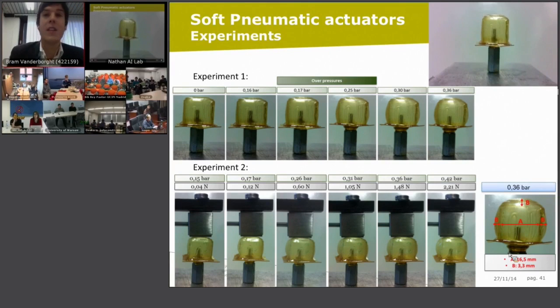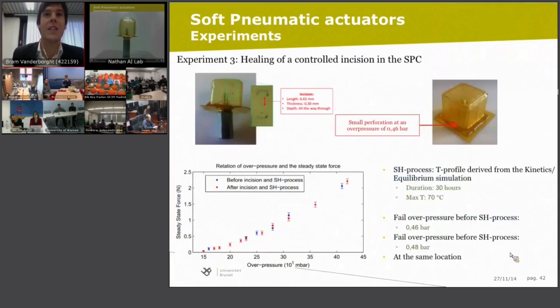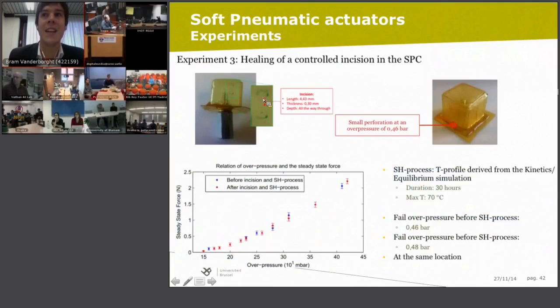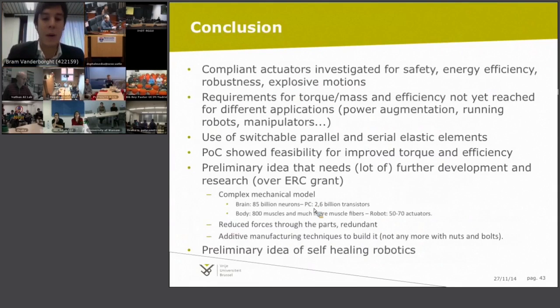What is the advantage of it? We can add a cut in it. So here you see that we made an incision in it. Also, once there was, by an overpressure, a perforation at the side, and then we self-healed the pneumatic actuator, and we measured again the force at different overpressures, and you see that the properties of this cell are exactly the same. So that means that these actuators are completely rehealed after having a cut or an overload of the material.